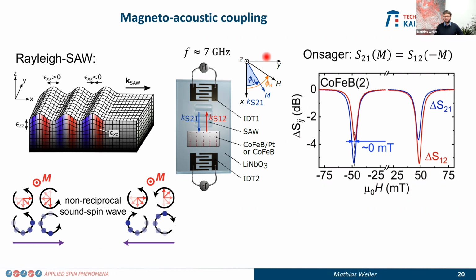And we can apply an external magnetic field. So here we apply it in the film plane. The frequency of the surface acoustic wave is here 7 gigahertz. And on the right-hand side, there are the experimental results that we obtain if we just use a blanket cobalt iron boron thin film. Okay? And in this cobalt iron boron thin film, having the surface acoustic wave passing through it, what we observe is a non-reciprocal behavior.